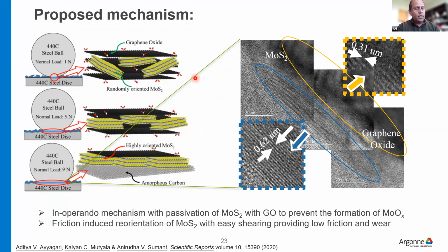The mechanism that we think here is GO basically acts as an encapsulation mechanism, which protects against the degradation of the sulfur in the MoS2. When you put higher energy into the system, like high contact pressure and high sliding speed, there is a recrystallization orientation of the MoS2, and that's why we are getting nice friction because of the sliding of the MoS2 lanes against each other. But as you go into the air, I think there is a degradation of the GO that happens with time, and once the GO cover is gone, that's where I think we see the failure. Nevertheless, I think we see a very interesting mechanism of protecting the MoS2 by using a GO, and a much higher lifetime as compared to the thin film coating.